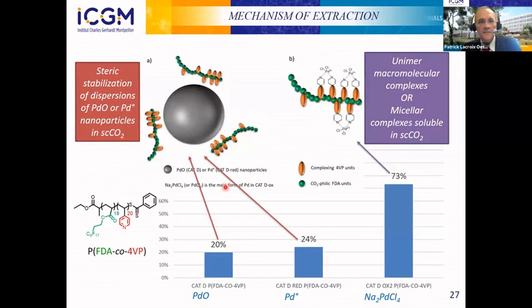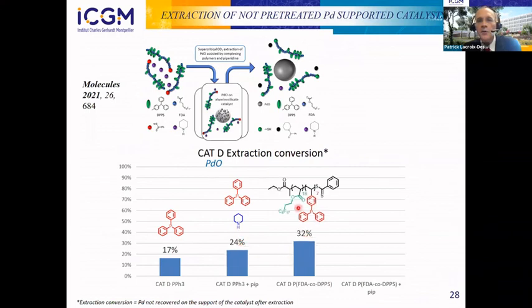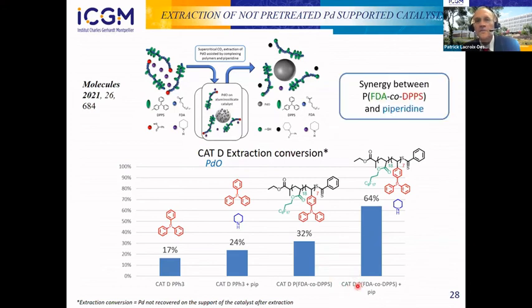For the virgin catalyst the extraction was not so good, so we tried to improve this by formulating the extraction mixture. Phosphine alone and phosphine with piperidine gave modest improvements. The polymer alone was not bad, but when we mixed the polymer with piperidine, we had a good surprise: 64% extraction conversion starting from the virgin catalyst without any pretreatment. There appears to be a synergy between the copolymer and piperidine that we need to continue investigating.